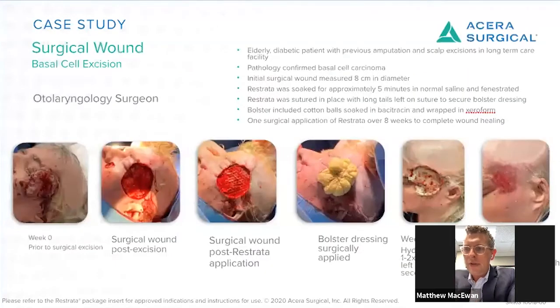Here's another interesting one. This is an ENT case where we had a large basal cell carcinoma removed off the side of a woman's face and treated that defect with the Restrata material. We were able to get very good filling and closure of that defect with very minimal scarification. So there are some really interesting applications now for this material in that space, especially the post-Mohs wound space, an area we're looking at quite a bit.